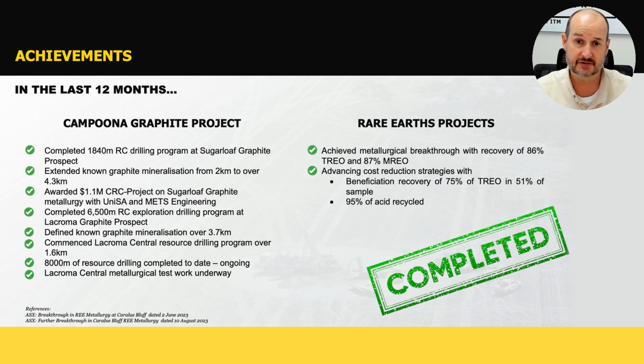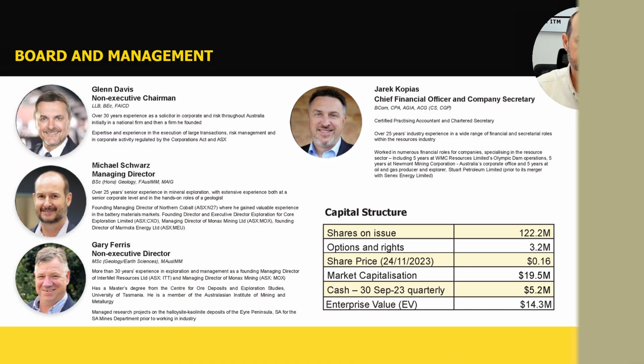So the two things we've achieved so far is that we've been able to beneficiate the material that we're leaching. We've been able to sieve it and get all the quartz grains out and leave the clay behind with the rare earths. And what that does is that leaves 75% of the rare earths in about half of the material. So we only have to process about half of the material we would normally. And the other thing is that we've been able to recover or recycle 95% of the acid that we're using to leach out those rare earths. So that will lead to a significant cost saving in the cost of acid. So quite a few achievements this year that we're very proud of.